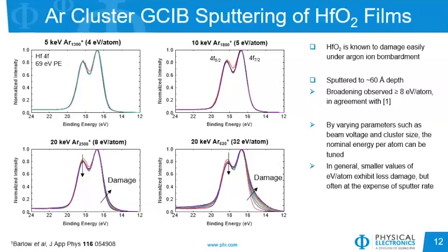And if we look at the change in the spectra as we profile through these materials, we do see that as we increase the eV per atom, we are seeing changes in the spectra, as in reduction of the 4f5/2 peak and a broadening to lower energy, which is related to reduction of the hafnium oxidation state.